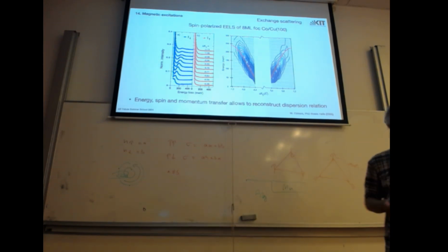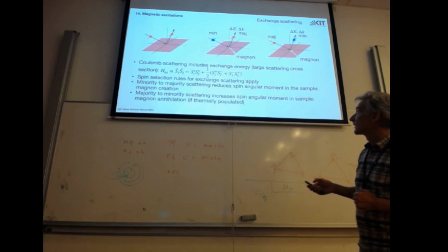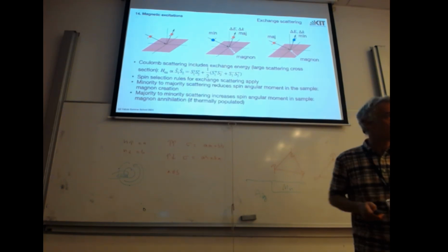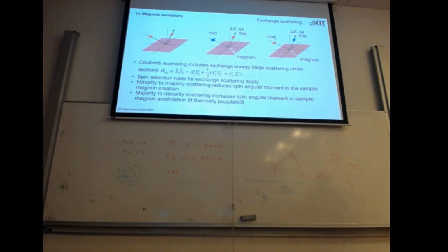Okay. The electron is created by photoemission from gallium arsenide with circularly polarized light. So the spin polarization is given by the circular polarization of the light, along the direction of light propagation. And the other spin is given by the magnetization of the sample. I can apply a magnetic field and saturate the sample in either of the two directions, parallel and antiparallel. It's not necessary to also measure the spin of the reflected electron.